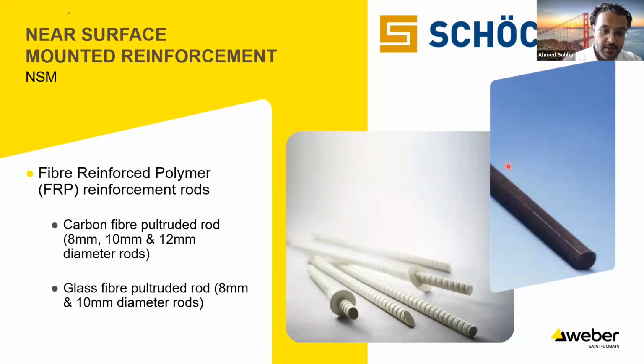The rods that you see in front of you here are ribbed rods, which play an important part in increasing the bonding and decreasing the slippage of the rods from the structural adhesive. And obviously they can be provided in different thicknesses. We're talking about 8 to 10 millimeters of thickness, dependent on the design.